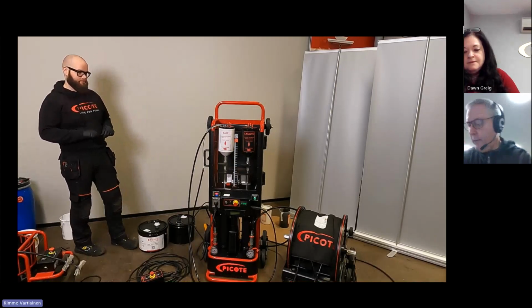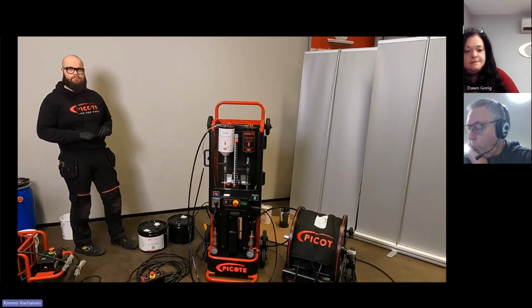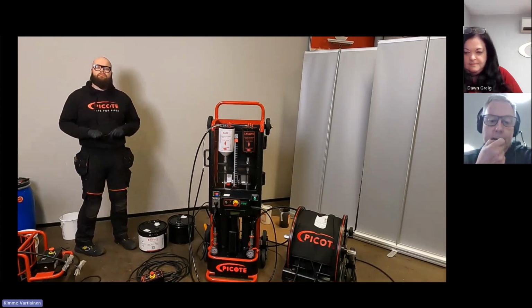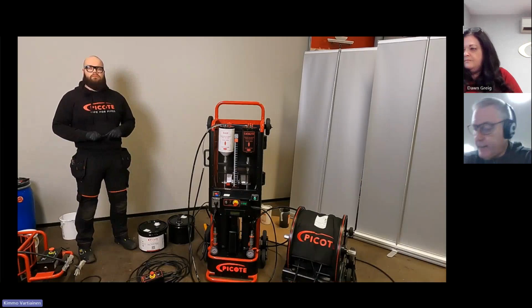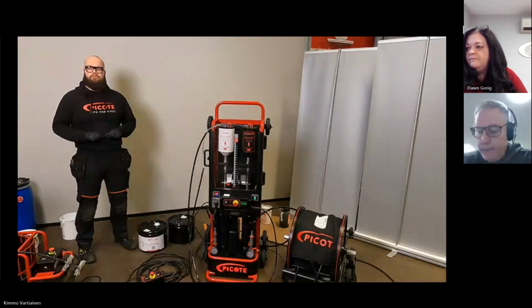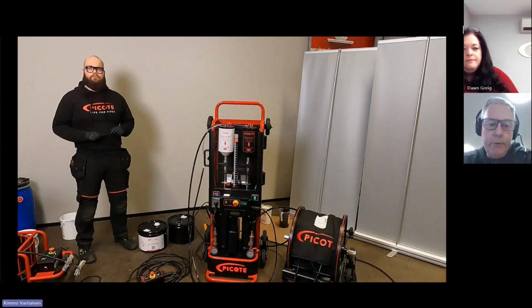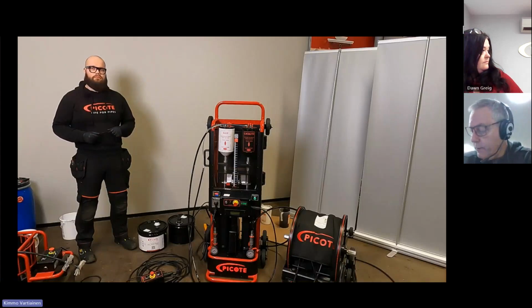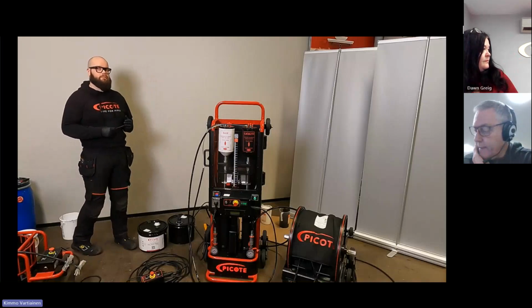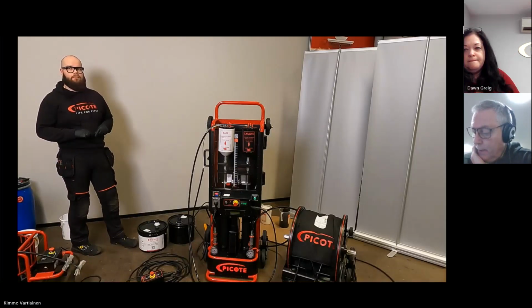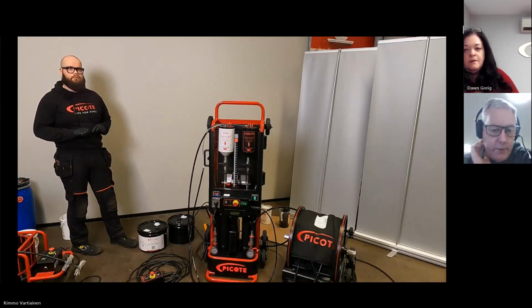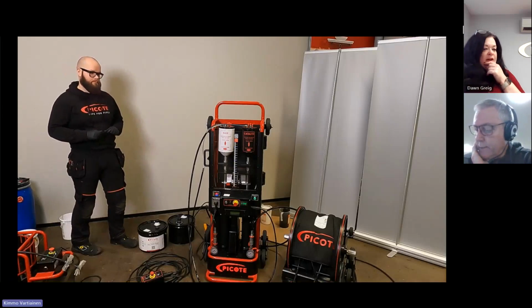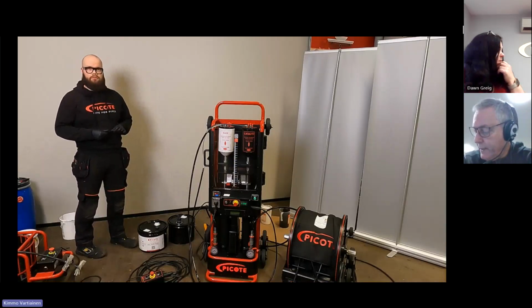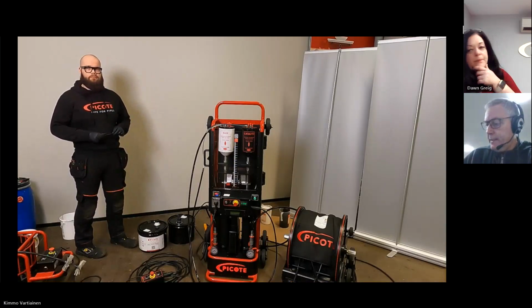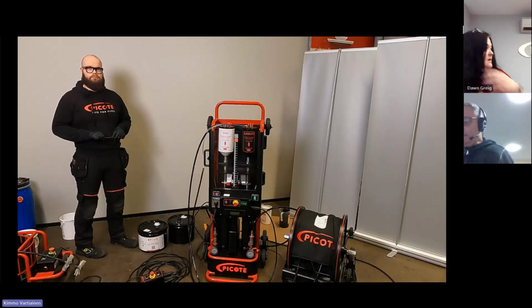Sorry, I'm just double checking. So it's a 1-to-1 mix ratio. We apply it in coats of 1 millimeter thick. The cure time between coats is somewhere between 1 to 1.5 hours, depending on cure time. Full return to service is 3 hours. Once you've opened the tins, the resins have a shelf life of 2 years. As I said, it's a mixed ratio of 1 to 1.